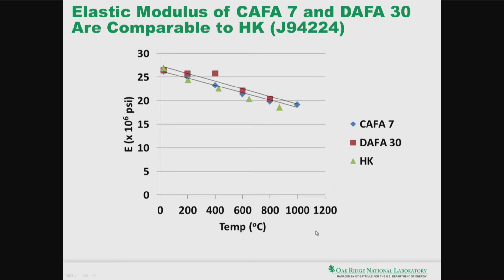What I'm showing you here is the elastic modulus as a function of temperature for these two alloys, CAFA 7 and DAFA 30. And you can see that the HK alloy slightly has a lower modulus, and if you're familiar with the data book, the HN and the HP are actually even much lower than these alloys. So if you are targeting applications that would traditionally use HK, this would be a good drop-in substitute for some of these alloys, but with the advantage of improved oxidation resistance.